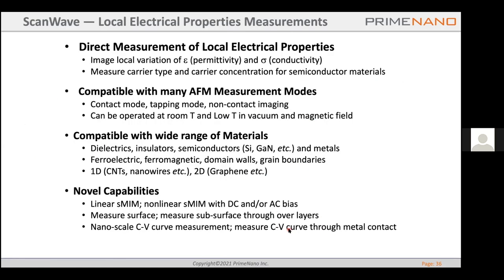So, okay, let me give the whole summary of this talk. So scanwave sMIM is a local electrical property measurement. It can directly measure the local electrical permittivity and conductivity. For semiconductor samples, it can measure the carrier type and the carrier concentration. And it's compatible with many AFM measurement modes, for example, contact mode, tapping mode, non-contact mode, for example, nap mode, peak force tapping. It can be operated at room temperature and also at low temperature, in vacuum and with magnetic fields.